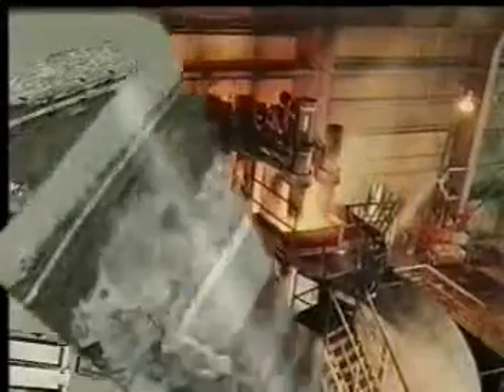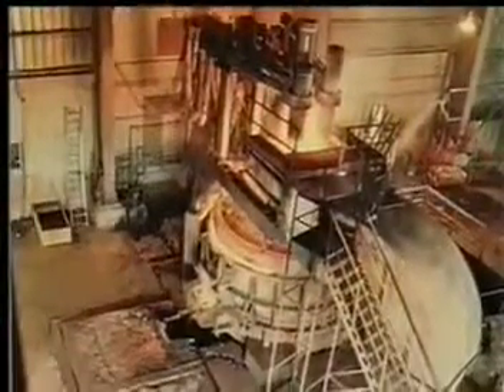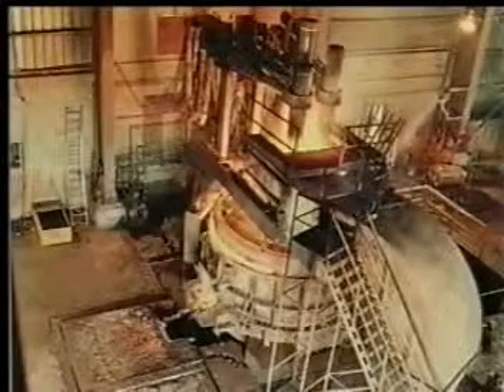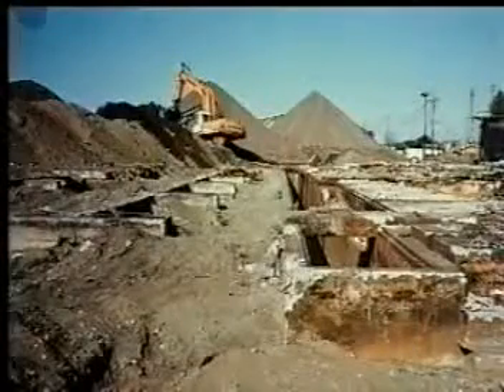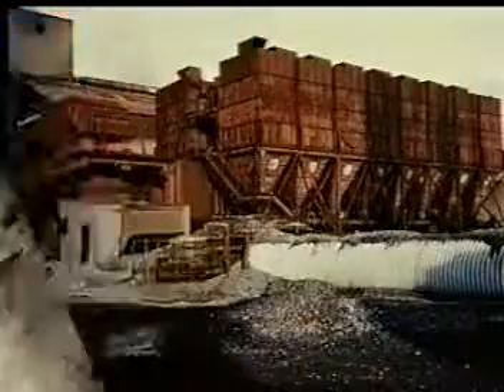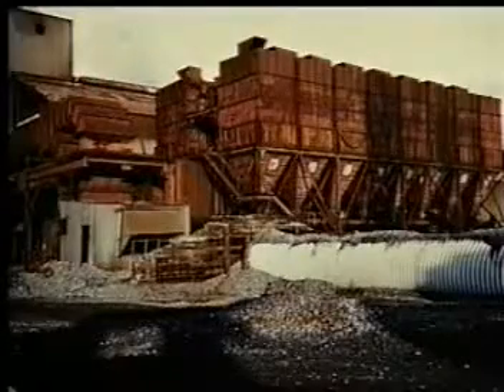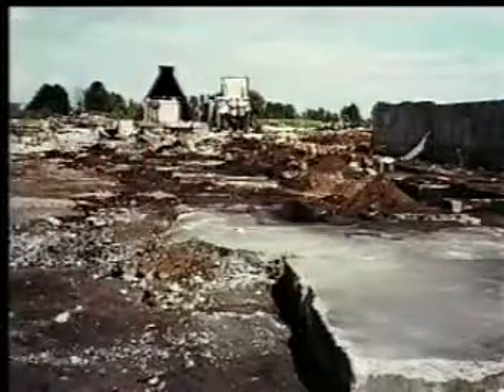As a result of the remediation of a former steel mill, 50,000 metric tons of leachable hazardous waste was recovered. The source of the waste was from on-site settling ponds used for containment of electric arc furnace dust. This dust was generated as a result of the melting of scrap metal used in the steelmaking process. Although pockets of the waste existed in relatively pure form, most of the waste was intermixed with native soils. Electric arc furnace dust is a listed hazardous waste having high concentrations of numerous metals.